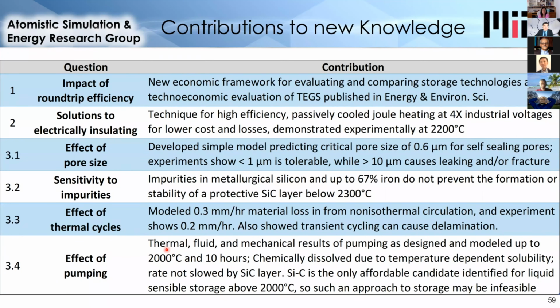This was also observed in pumping, despite the fact that from a thermal, fluid, and mechanical standpoint, the pump worked as designed. And at least this bodes well for a future material pair, such as carbon and tin, where there's no chemical interaction between the two. So we do know that it is possible to pump at these temperatures. And so if more compatible materials are used, potentially we can circulate tin at these temperatures in this alternative embodiment I discussed.